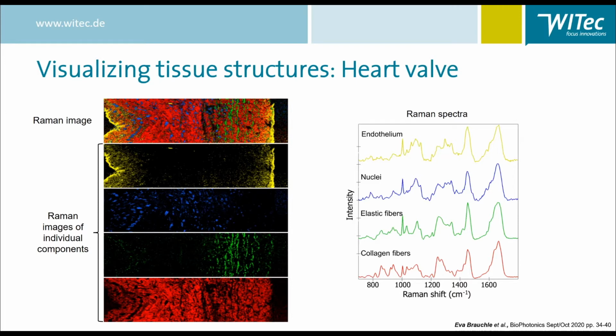Corresponding Raman spectra are shown on the right in the same colors. The collagen fibers are colored in red in this image, with the endothelium in yellow marking the outer interface. The elastic fibers that are embedded in the collagenous matrix are clearly visible in green color. This elastin-rich layer marks the blood inflow site of the valve.